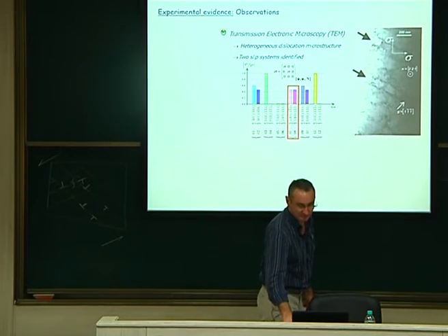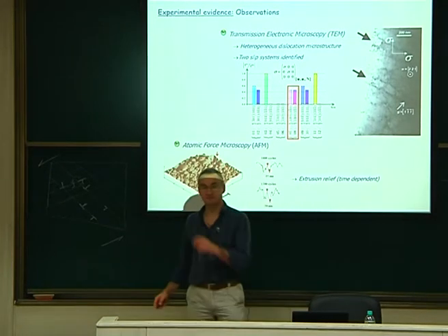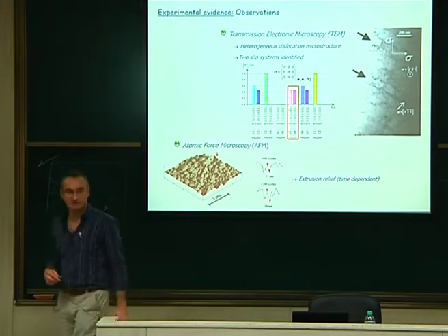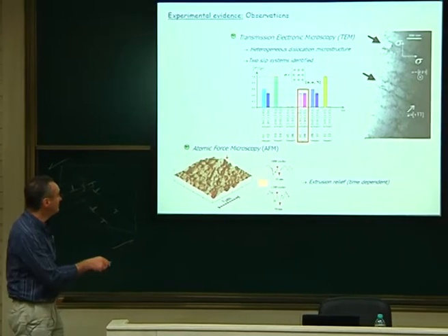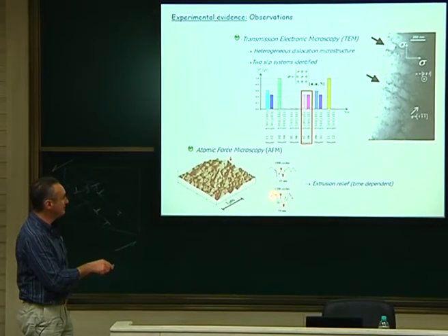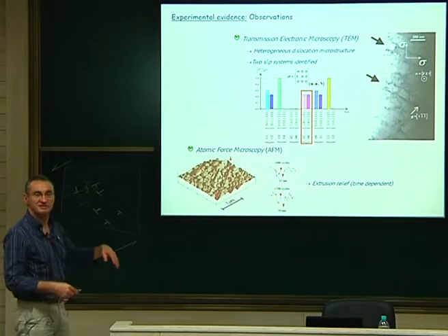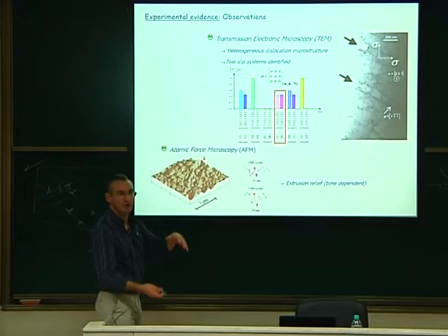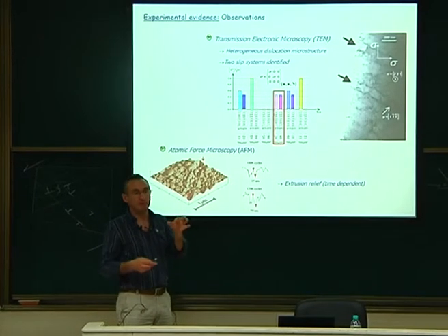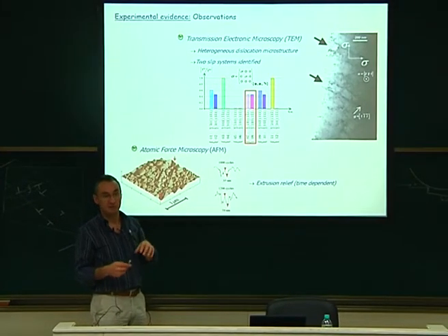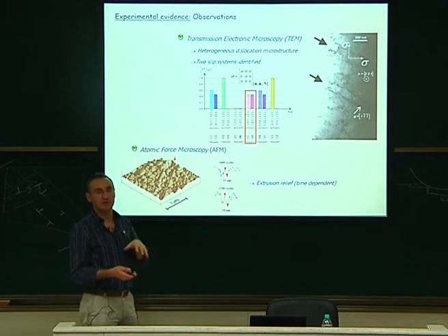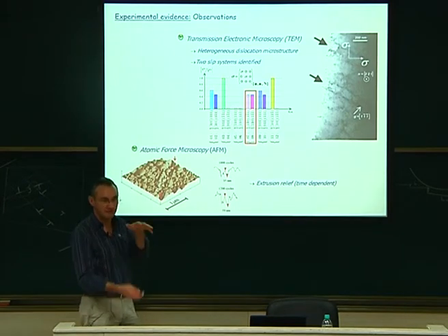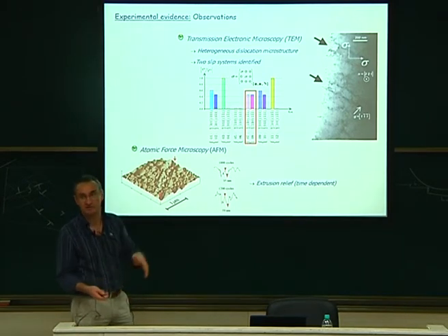So let's go further. Now, if you look at the surface, how does the surface of your specimen look after a few cycles? This is after 1,000 cycles, 1,200 cycles. By the way, this is low cycle fatigue. We call it low cycle fatigue. It means that the loading is quite big, although we are just imposing 0.1%. This is 0.1% plastic strain. So it's not high cycle fatigue. This is low cycle fatigue. The life is quite short.